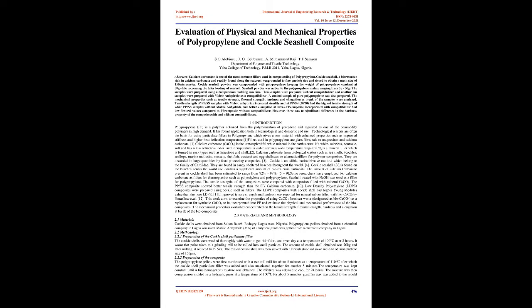Tensile strength of PP/SS samples with maleic anhydride increased steadily, and PP/SS 50/30 had the highest tensile strength, while PP/SS samples without maleic anhydride had better elongation at break. PP composite incorporated with compatibilizer had low flexural values compared to PP composite without compatibilizer. However, there was no significant difference in the hardness property of the composites with and without compatibilizers.